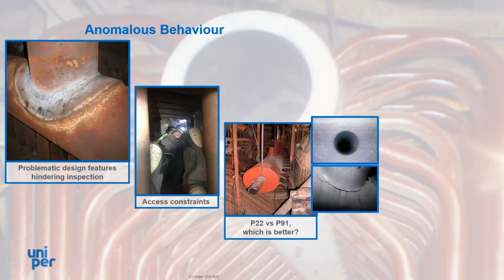And there have also been instances where grade 22 components have been replaced with grade 91 in anticipation that this will greatly extend the life of the component under a cyclic operating regime. Instead, what we've ended up with is replacing the star cracking around stub welds with circumferential cracking at the same stub welds on the external surface, often resulting in very little extension in the component lifetime.